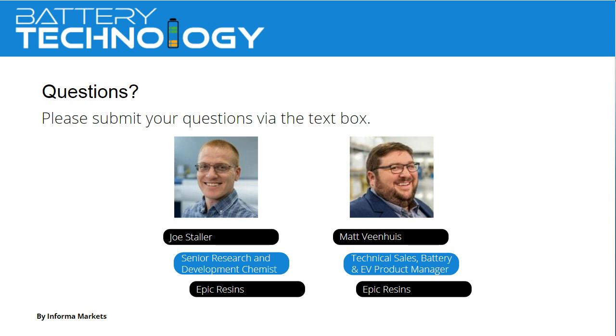Someone wants to know, using different words, when investigating component failures, how does one rule out potting failure? A couple ways we can do it here: we have an FTIR microscope. We can section a customer's component and do an FTIR analysis of different cross sections to determine whether the polymer itself had any failures, either from a thermal standpoint or a processing standpoint. We can determine that by comparing unthermocycled polymer to thermocycled or thermoshocked polymer, or whatever environment that polymer was in, using that FTIR technology.